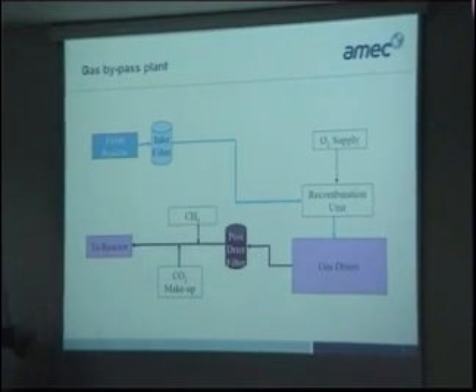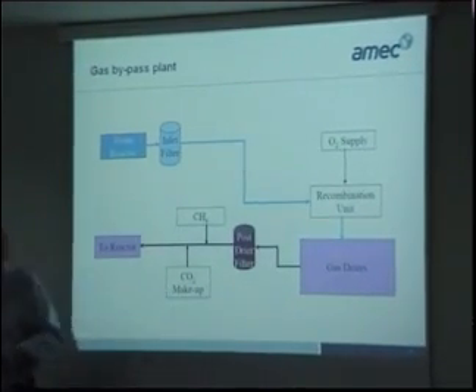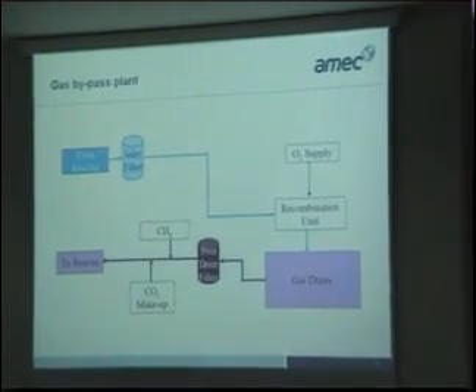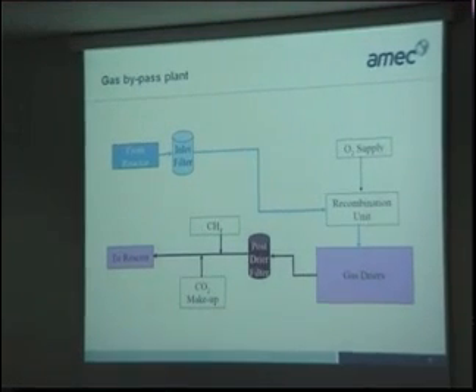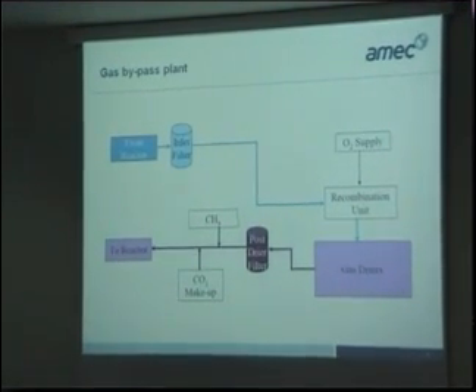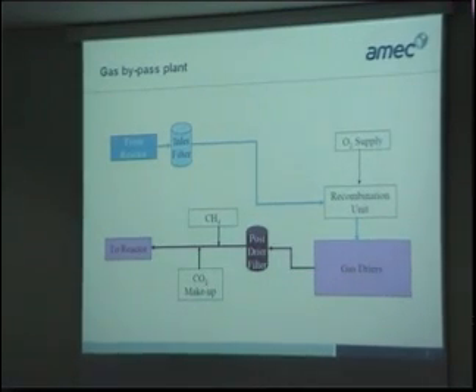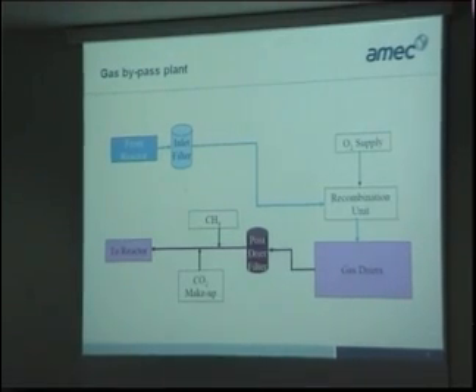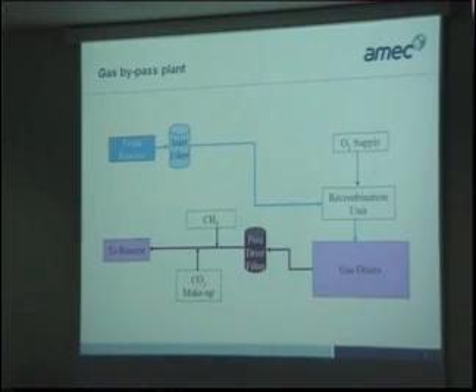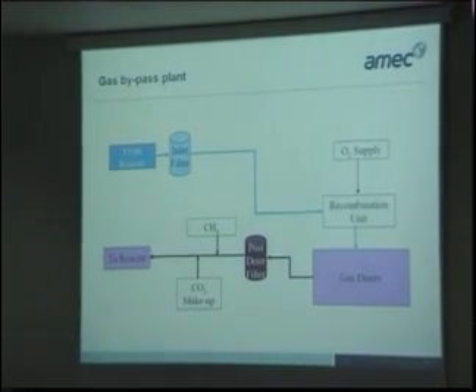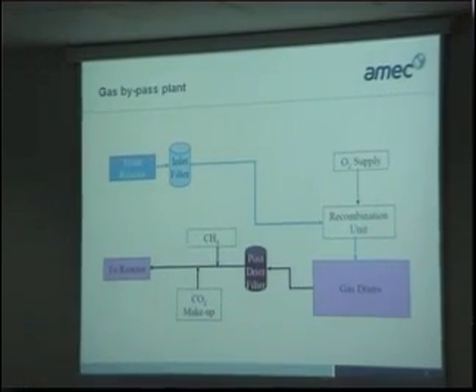The water vapour, which is produced all the time, is controlled in the gas dryers, and this is a desiccant, and usually there's either 2 or 3 of these desiccant towers, depending on the reactor design: one in standby, one in operation, and one regenerating. You can regenerate them. They absorb water vapour at a relatively low temperature, and then to drive the water vapour off, once they become saturated, you heat them up and condense the water. And this is usually done on a time cycle. Incidentally, the water that comes off the dryers will be reasonably concentrated in tritium. So tritium is a main radioactive discharge here from the AGRs.